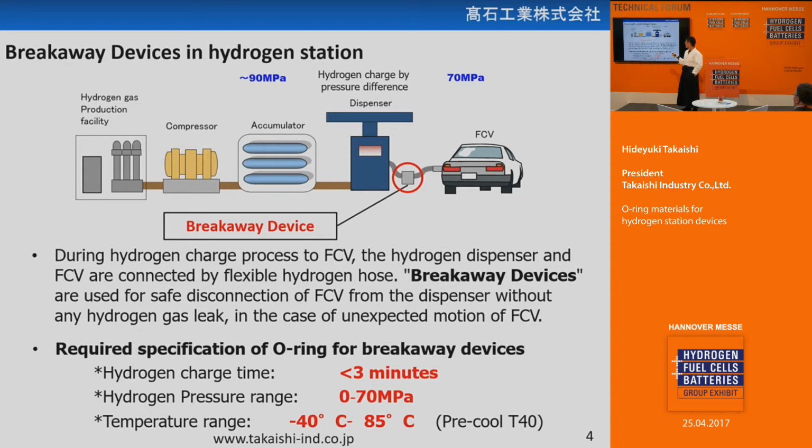The required specification of the O-ring for these devices is like this. Charging time is less than 3 minutes, like a gas station. The hydrogen pressure range is 0 to 70 megapascal, which means 700 bar. It's very high pressure. And the temperature range is minus 40 degrees to 85 degrees. This condition is too much for normal rubber material. Normally, only metal seals and metal gaskets would be applied. But we made some solution,